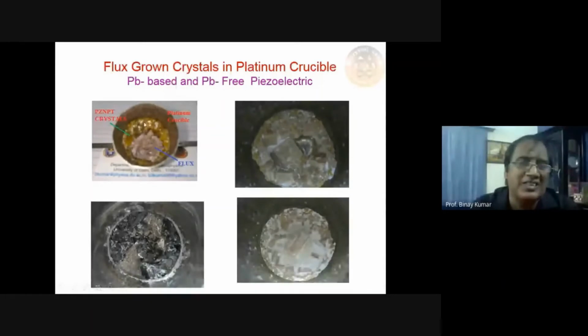This is a very difficult task, to take out this material, because in most cases we have to put this whole crucible inside HNO3, that is nitric acid, which is heated, and it takes weeks and weeks, 10 days, so that we can dissolve the flux and take the crystals out of it. But these crystals are so strong that nothing happened to them, even inside hot concentrated nitric acid.